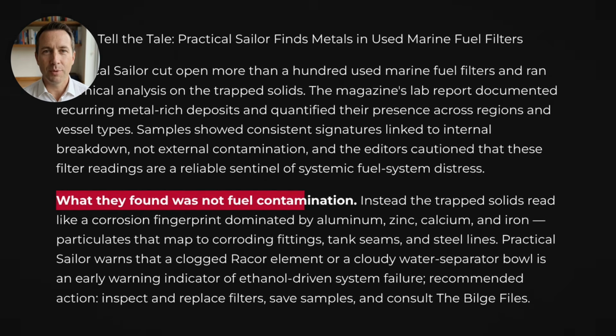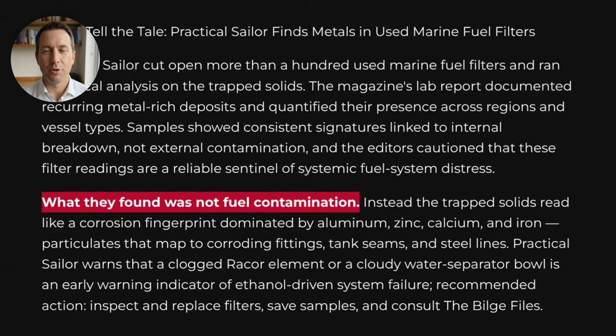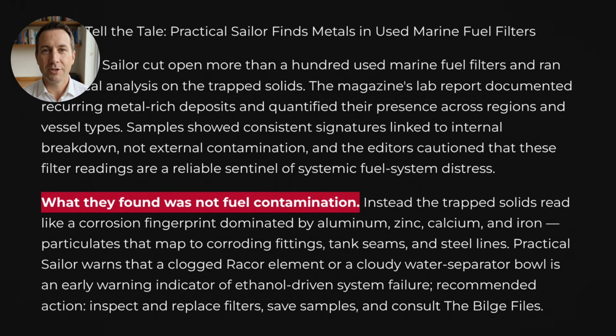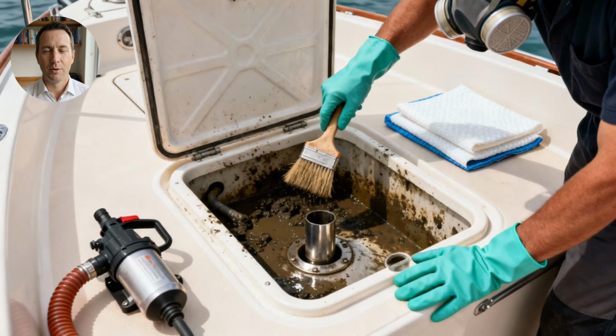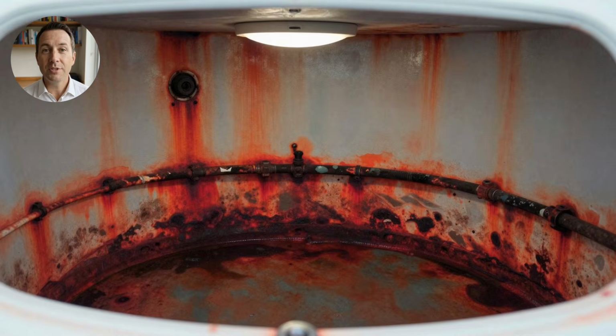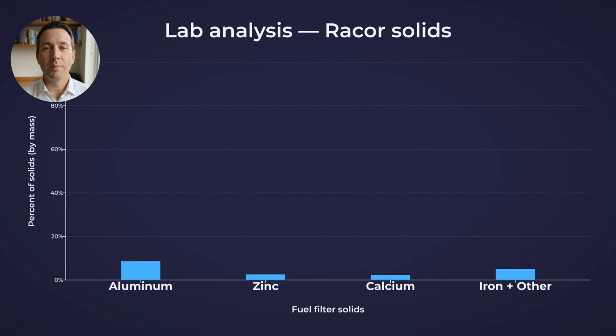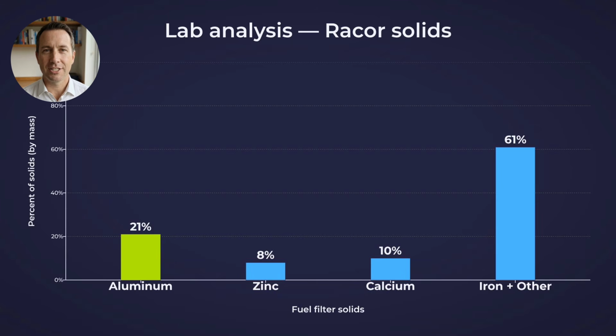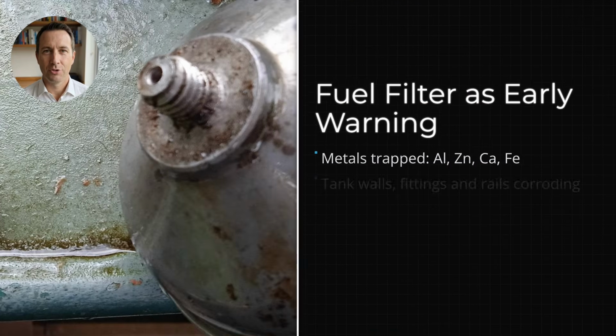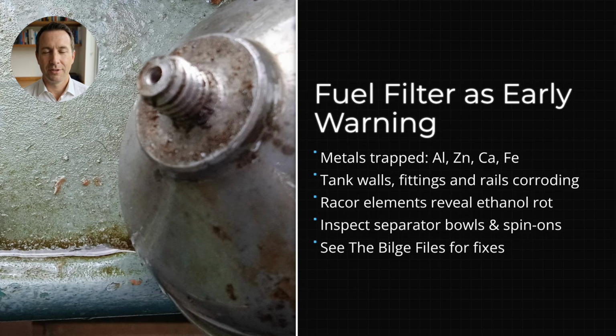Practical Sailor cut open more than 100 used marine fuel filters and ran chemical analysis on the trapped solids. What they found was not fuel contamination, it was the fuel system itself being digested. The solids contained 21% aluminum, 8% zinc, 10% calcium, and 61% iron and other metals. Those are the metals from the tank walls, the fittings, the filler neck, and the fuel rail being corroded away and caught in the filter element.